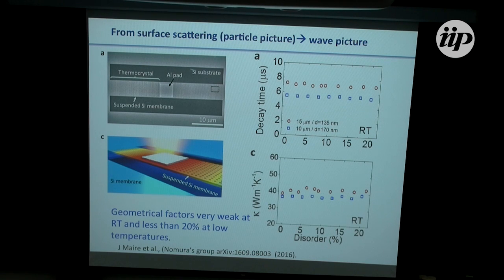These measurements were confirmed by the group of Professor Nomura in Tokyo, where they had a similar arrangement, only here a stripe and a square pad, because they perform time differential thermal reflectivity, suspended structure, etc. And what is important is that they saw, like us, no major influence on the decay time, and more to confirm our data, no variation with respect to disorder at room temperature, both order and disorder. So at least the dependence of the thermal conductivity on positional disorder has been confirmed independently. This is very positive for us, and with a different technique, actually.